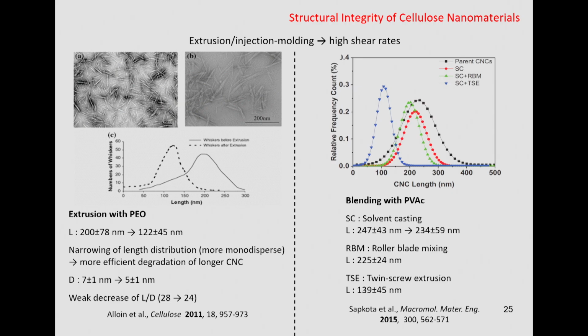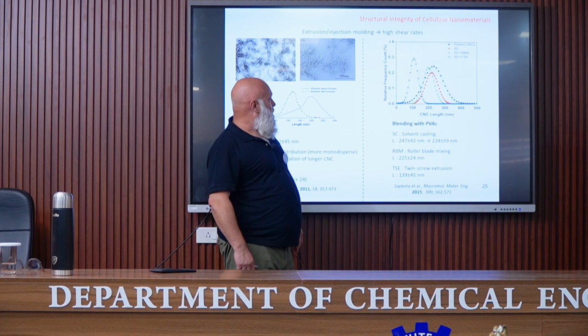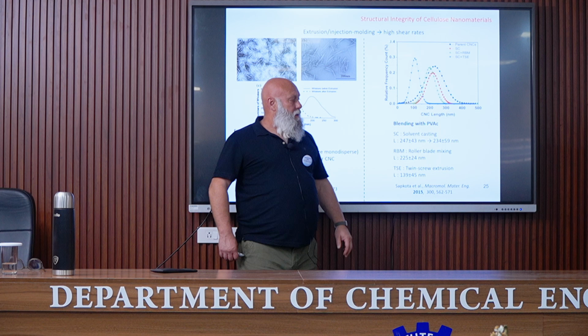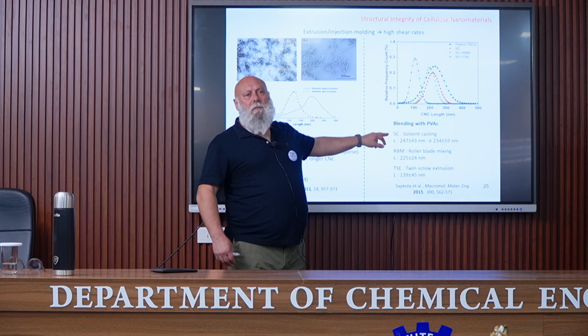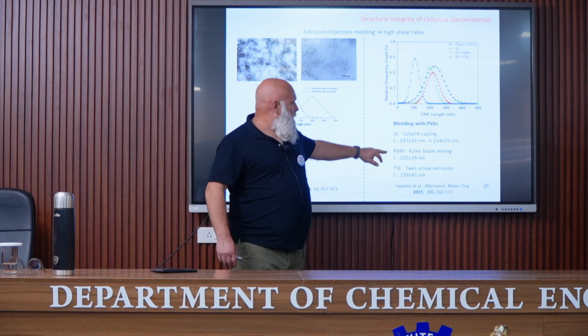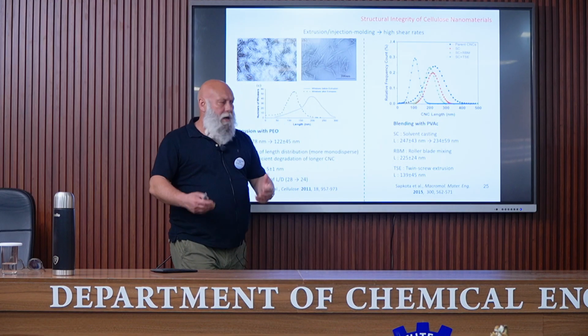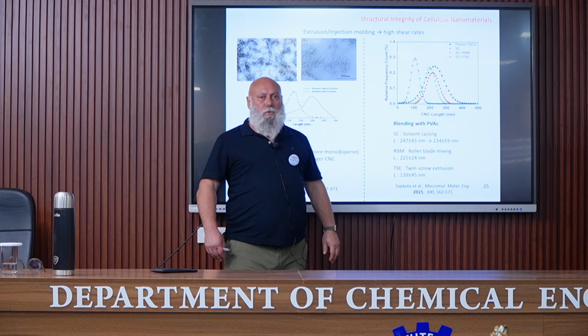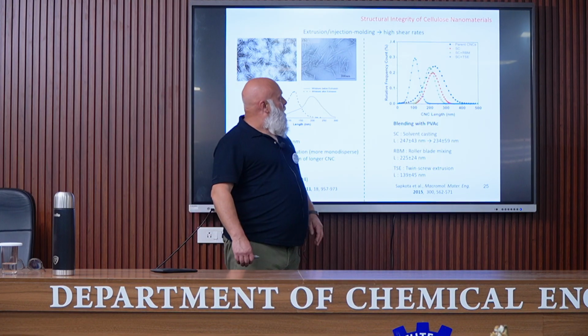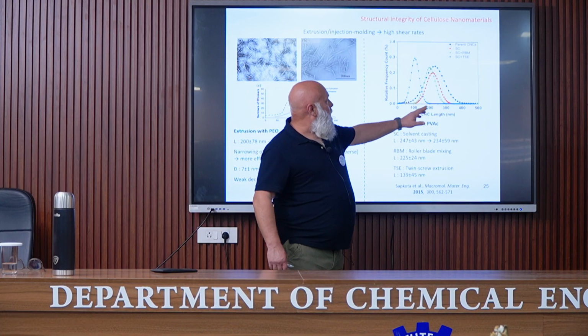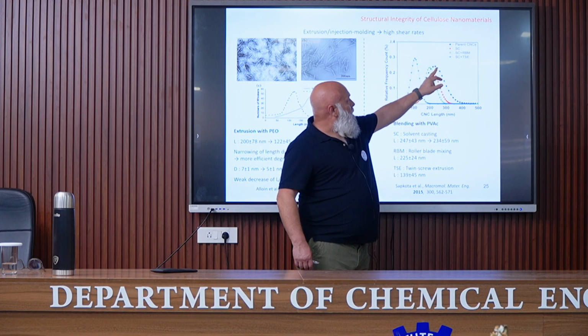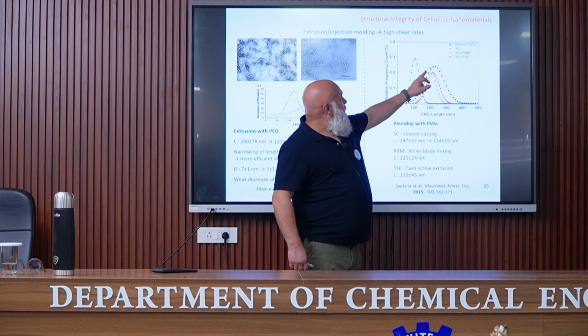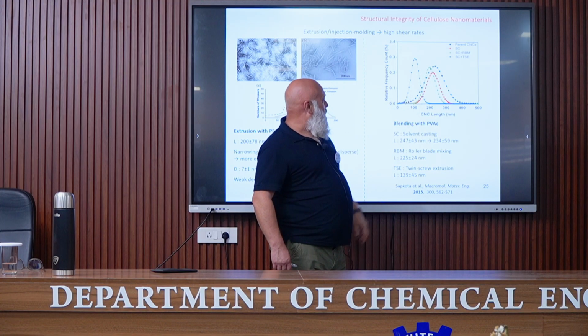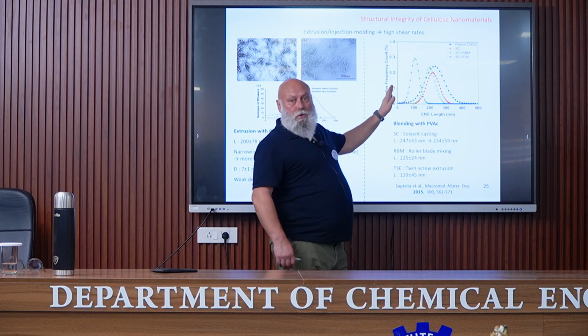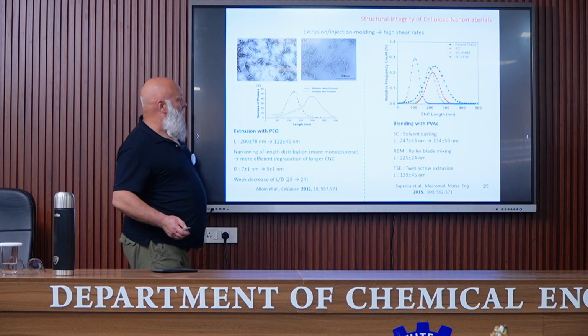This is another example in which different processing techniques have been used. It was with polyvinyl acetate as the matrix: solvent casting, where no shear rate is involved, roller blade mixing, with higher shear rate, and twin screw extrusion, with further higher shear rate. And we can see the length for the parent CNC, solvent casting in red, in green roller blade mixing, and for extrusion, we have a strong reduction in the length of the nanocrystals.